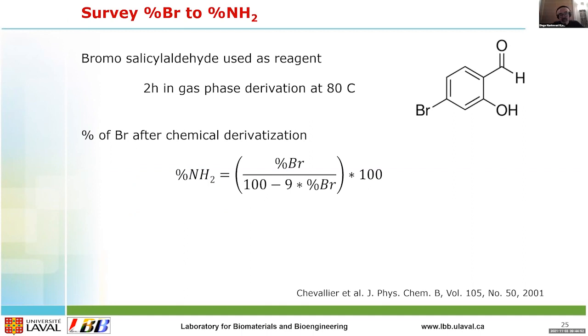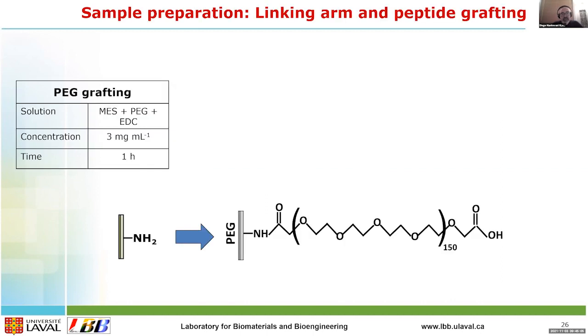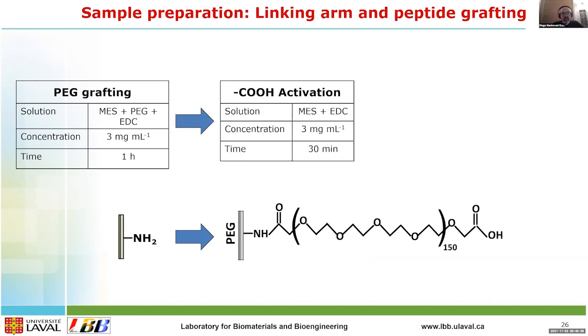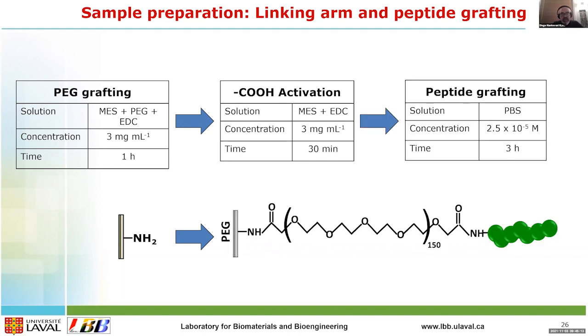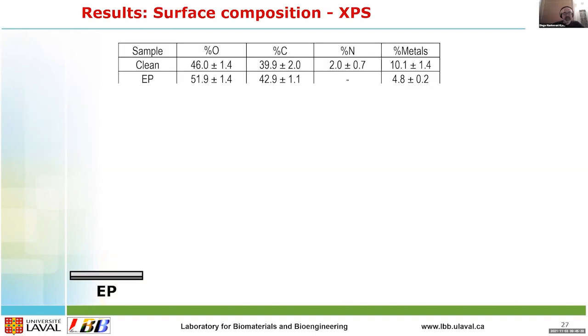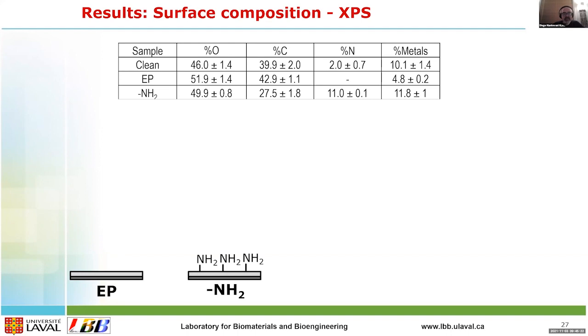And if you need to, through derivatization, you might be able to know exactly the percentage of amine groups present on the surface. So for the linking arm, this is what we did with PEG. Basically, we activate the carboxylic group, and finally we graft the peptide. Everything is reported, there is no real secret, and let's go to XPS.